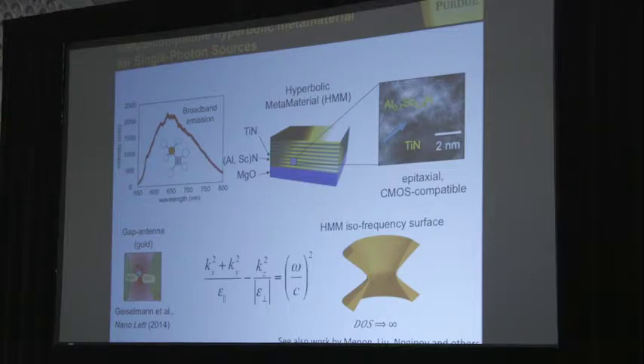Of course, in the end, it's still limited by the size of this structural unit, but that could be much smaller than the wavelengths, hundreds of times smaller. And we actually developed these hyperbolic metamaterials made of titanium nitride, which is a lattice match to dielectric layers, aluminum scandium nitride. And scandium was added here for the purpose of matching the lattice. So basically, we have 20 layers of titanium nitride, single crystal quality. Each layer is 5 nanometers thick. And 20 layers of aluminum scandium nitride, also single crystal quality, 5 nanometers thick. So it's like one single superlattice.